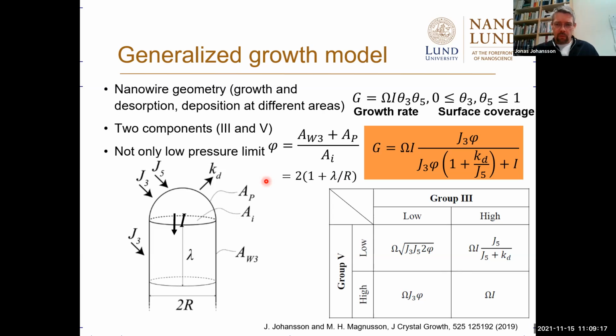So what is most interesting for ordinary, say MOVPE, maybe MBE growth of 3-5 nanowires, is that we have high group 5 and lower group 3. Then we have this relation. So the growth rate depends on flux of group 3 times this factor here, which is proportional to 1 over the diameter. So thinner wires grow quicker, as we have seen many times.